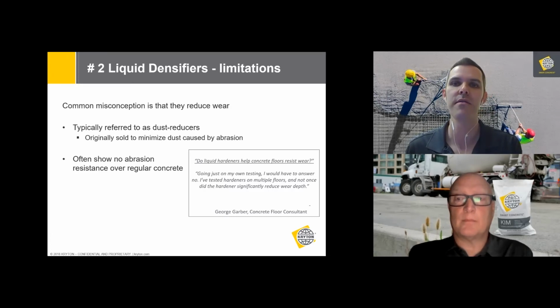Now, the reason for this is what we just touched on. These hardeners work by slightly increasing the amount of hydrated cement paste in your concrete. But we've already identified that the weakest component is the cement paste. Just having a little bit more doesn't really change the situation. It helps a bit, but not that much.